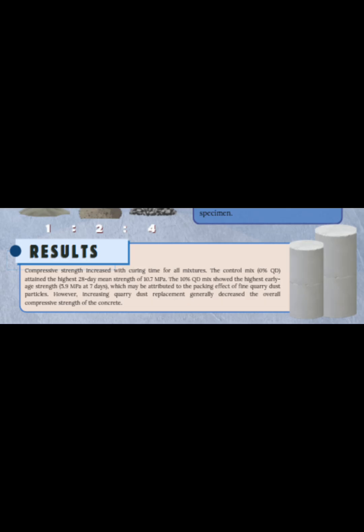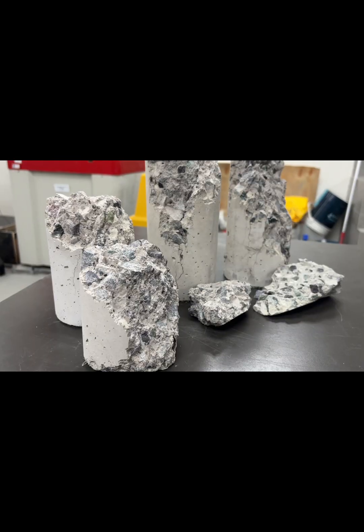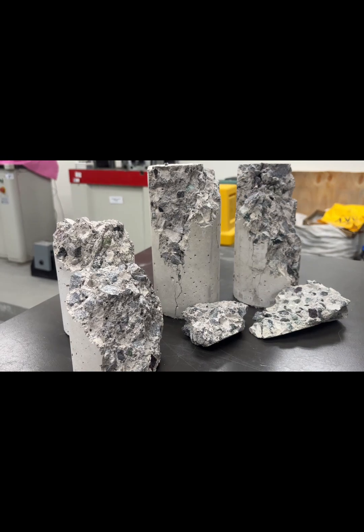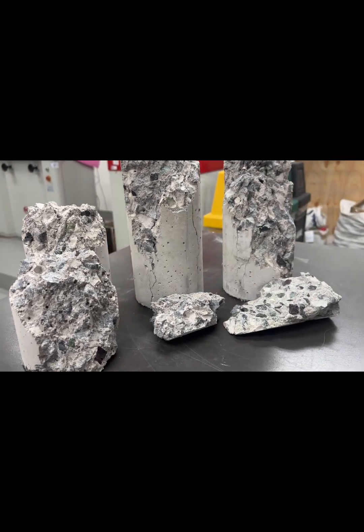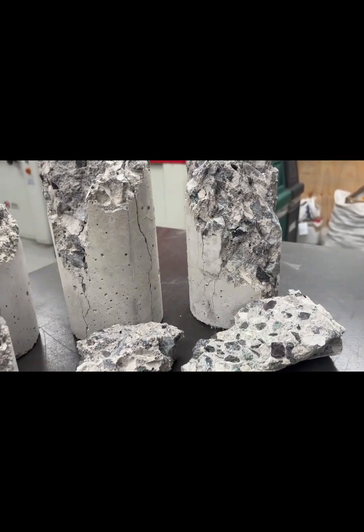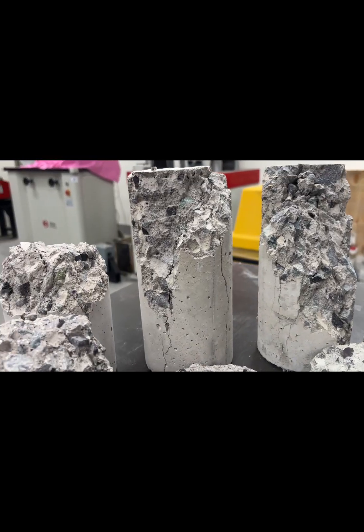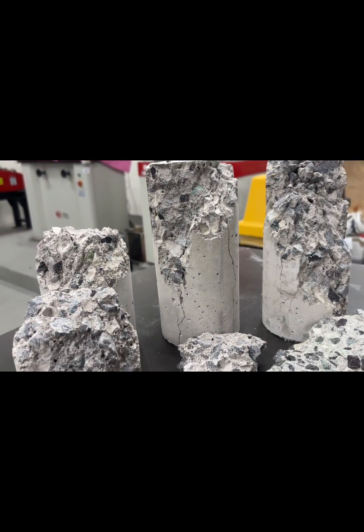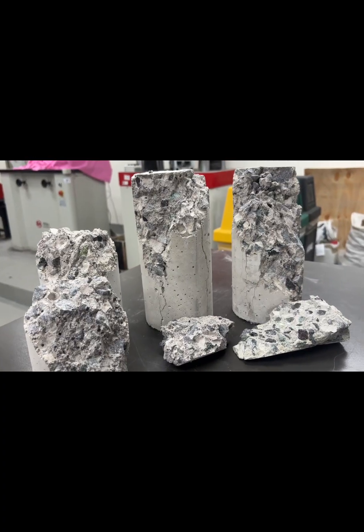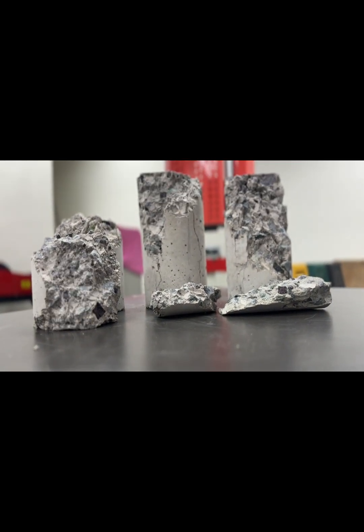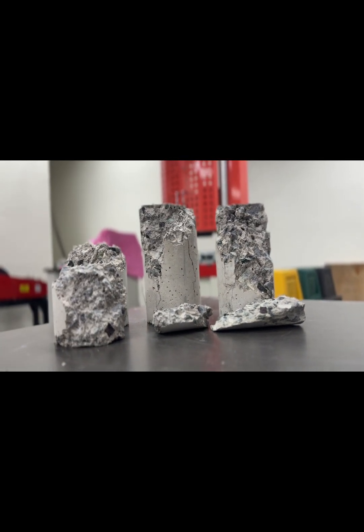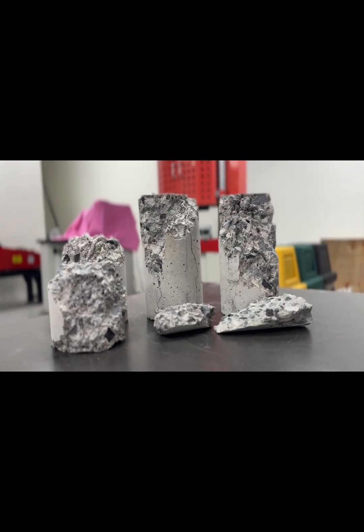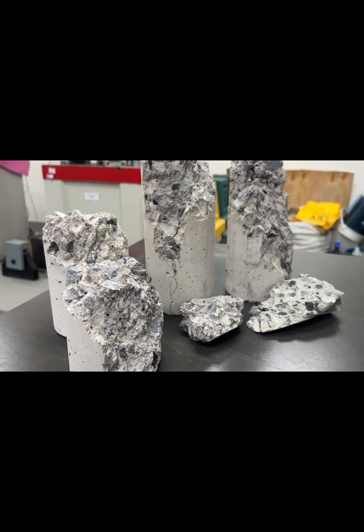Based on our results, compressive strength increased with curing time for all concrete mixtures. The control mix with 0% quarry dust produced the highest compressive strength, reaching approximately 10.7 megapascal. The 10% quarry dust mix achieved about 5.9 megapascal, while the 20% quarry dust mix recorded the lowest strength. Overall, increasing the amount of quarry dust generally reduced the compressive strength of the concrete.